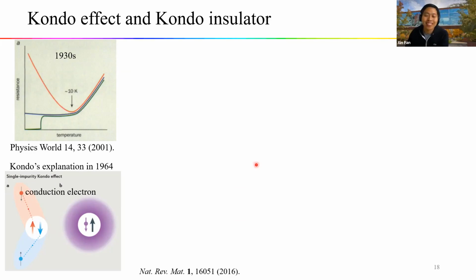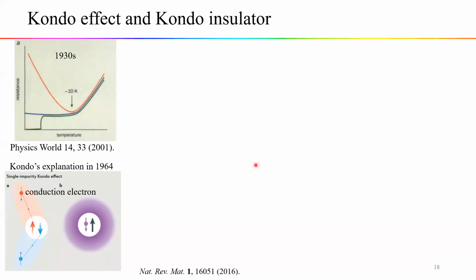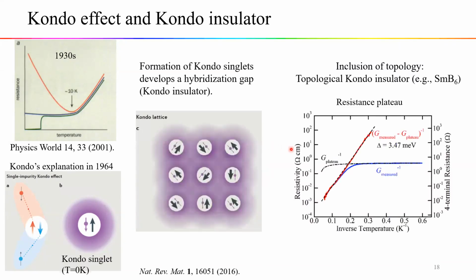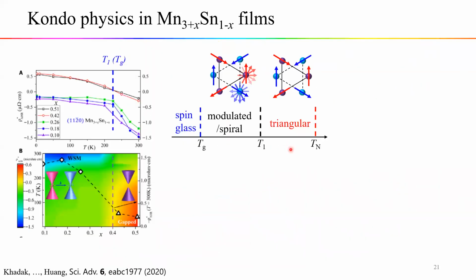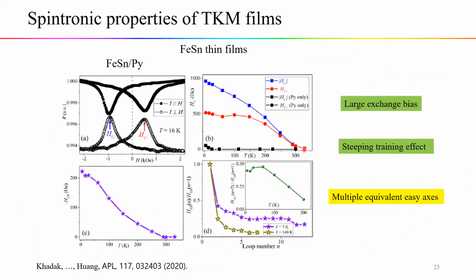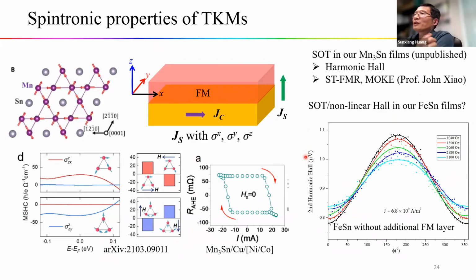Weyl, please go ahead with your question. Sunxiang, thanks very much for the very nice talk. Can you talk a little bit about this harmonic Hall effect? So what are you actually measuring? It seems like you need a lock-in amplifier. Yeah, we use a lock-in and we pattern the sample into the Hall geometry, and we apply the in-plane field, just like the spin orbit torque measurement in those materials. But this result comes from the Iron-tin layer without the magnetic layer.